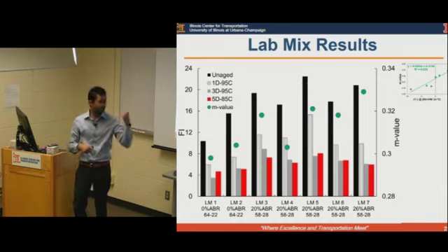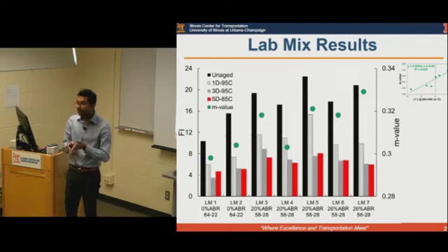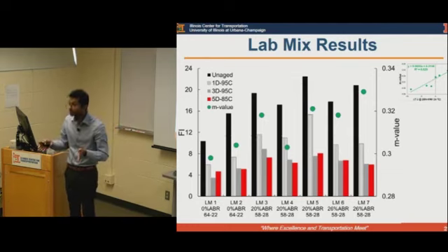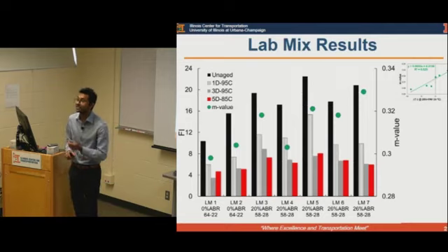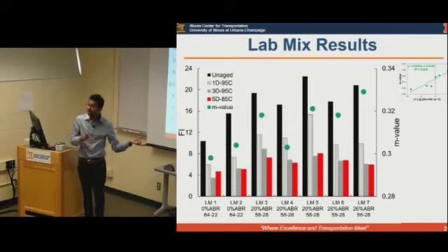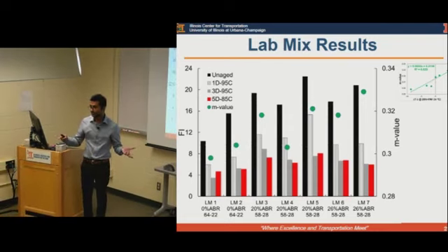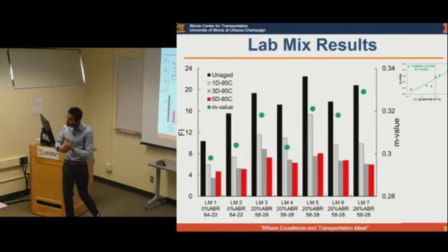And this is from one of the literature, I can share the literature. It said that in order to have that photo-oxidation take place, you need energy from, I think, 400 nanometers down to some nanometers, and UV falls under that range. That's why UV causes that photo-oxidation. So it's not the heating that causes it. Now, heating also causes oxidation.